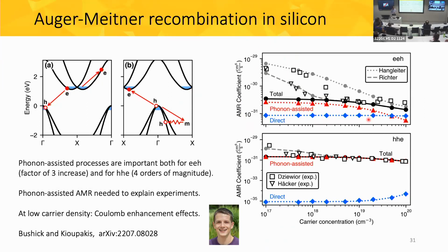So one may say that it's good enough, right? However, for silicon, we have very accurate data, so we can go one step further and try to understand if we can improve this. And in fact, we see that if we do factor in phonons that enable electrons to occupy any of these final states in the Brillouin zone, we get a much better agreement with experiment across this very high doping range.